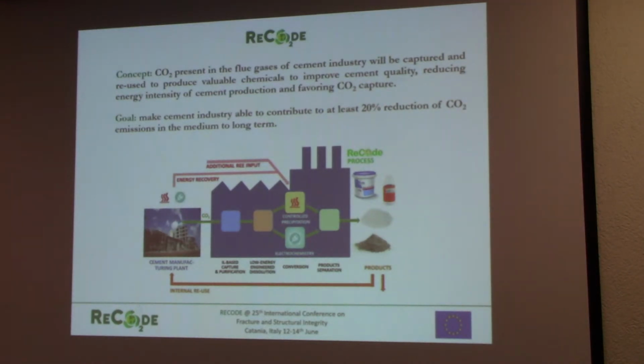The concept of the RECODE project is very simple. The gases in the cement manufacturing plants will be captured and purified with a low energy engineering dissolution, in particular by means of electrochemistry and controlled precipitation, in order to capture and reuse the CO2 emission in forms of valuable chemical products, in order to be reused, for example, to enhance the cementitious composites, or for example, for polymer. The goal, of course, is to make the cement industry able to contribute at least a 20% reduction of CO2 emission in the medium and in long term.